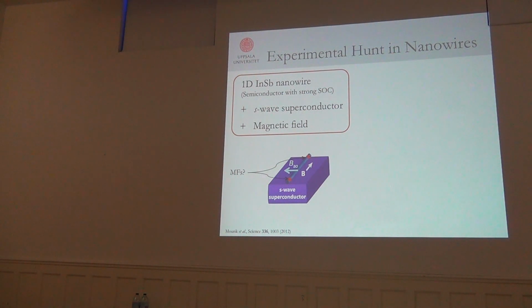The first example came out in 2012. They used indium antimonide nanowires, a semiconductor with reasonably strong spin-orbit coupling. They put it on an S-wave superconductor, maybe it was aluminum or something, and they added a magnetic field in this direction. The important thing for the 1D system is that the magnetic field is not in the same direction as the spin-orbit coupling in the wire. So the spin-orbit coupling in this case is this way, magnetic field this way.